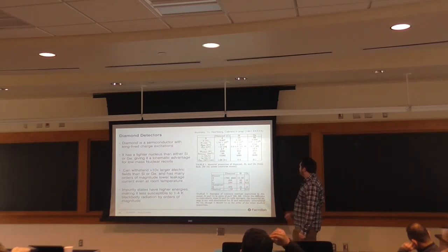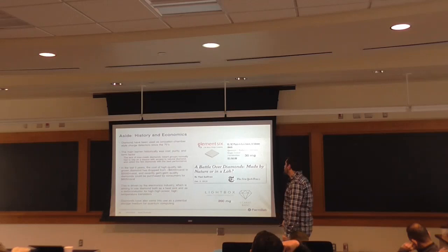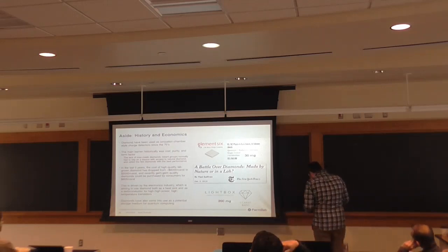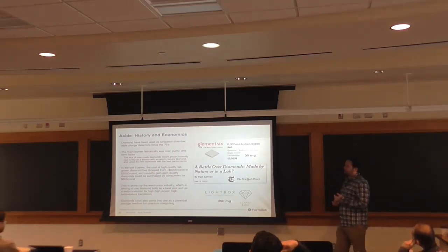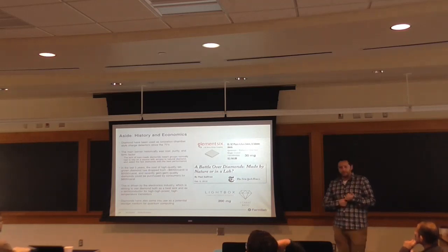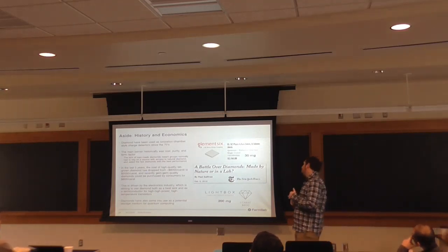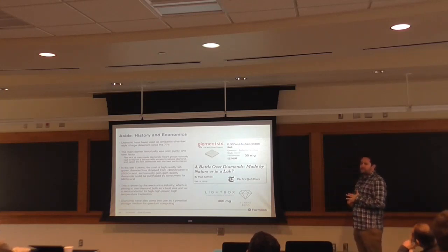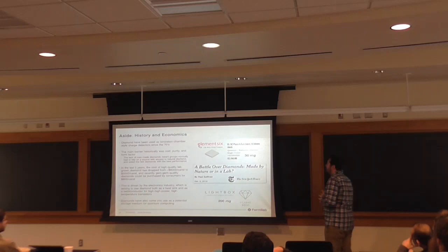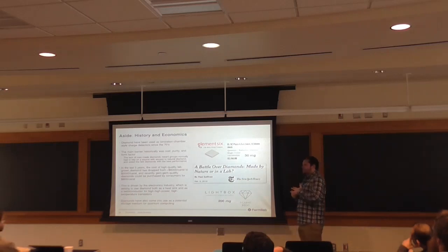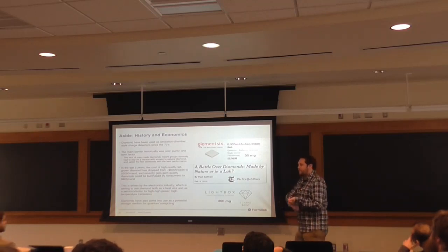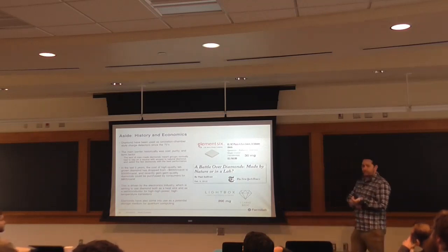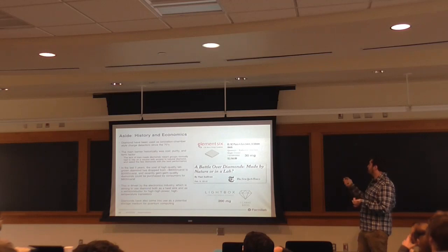Lithium, again, about 10 times higher energy. And this has become interesting recently because the field of artificial diamonds has changed substantially in the last 18 months. So since 2016, the price of artificial diamond has dropped by 80%, from about $5,000 to about $1,000. And a bunch of labs are now making it. So Element Six is owned by De Beers. Lincoln Labs is making this for qubit storage research, working with Element Six.